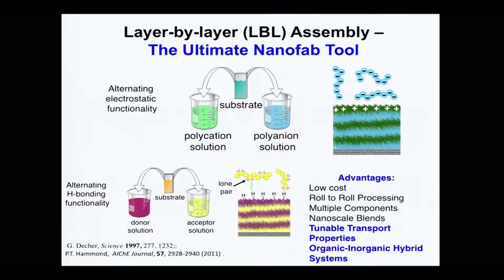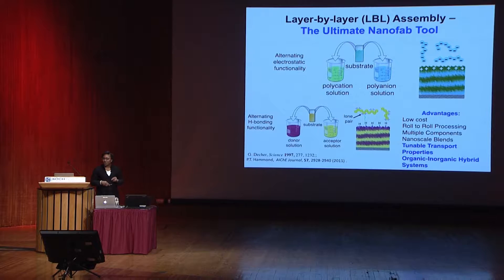The thickness of each of these layers can be controlled with pH and ionic strength, but they typically range from as thin as a half nanometer to as thick as tens of nanometers. What we can incorporate into these films ranges from small drug molecules to proteins to nucleic acids. This becomes a very compelling way of incorporating a drug into a thin film and getting a very high density or loading of that drug. Other complementary interactions can count as well—hydrogen bonding, disulfide bridges, and a range of other methods.